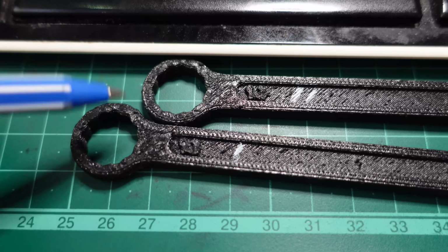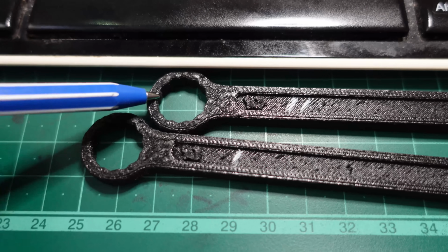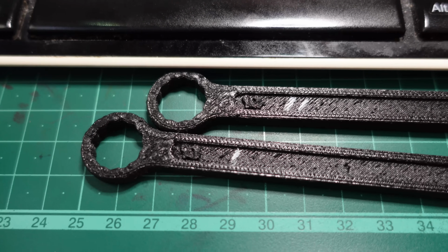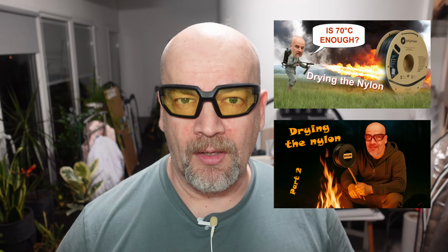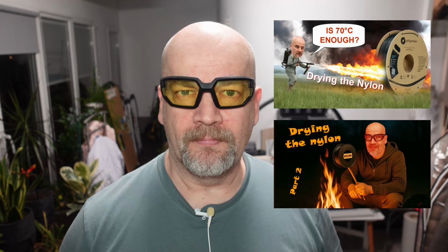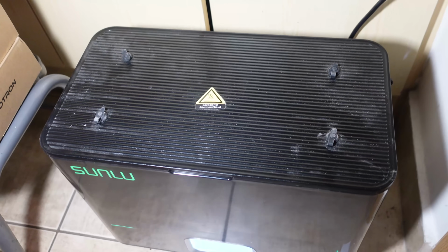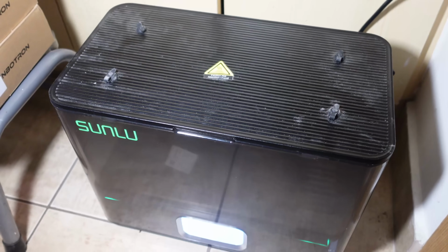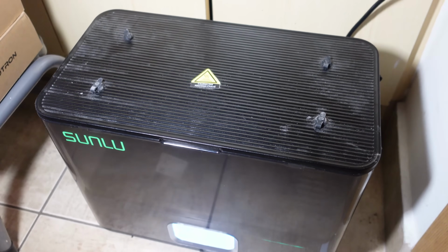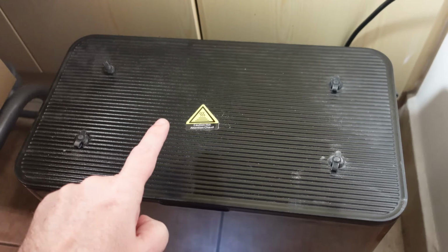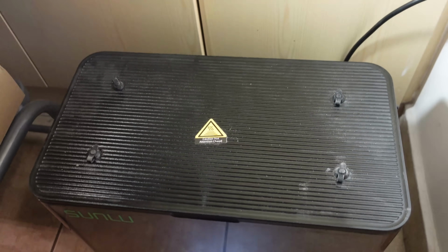This is the first version, and this is after additional drying at 70 degrees Celsius, almost 12 hours. I'm not really surprised. Depending on the starting moisture, drying at 70 degrees Celsius sometimes requires even one week, as tested in two videos. One last attempt: drying in the Sunlu E2 filament dryer at a little bit more than 90 degrees Celsius. I hope the spool will survive this temperature.